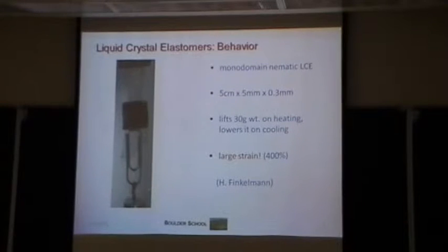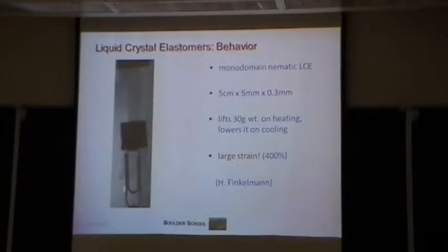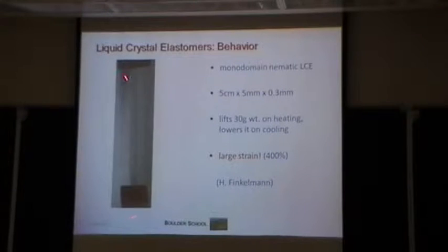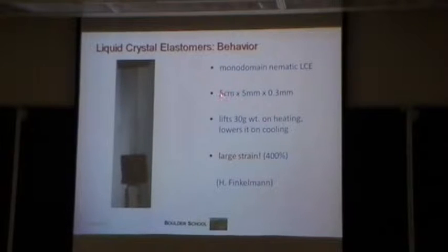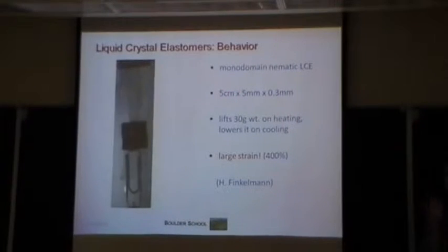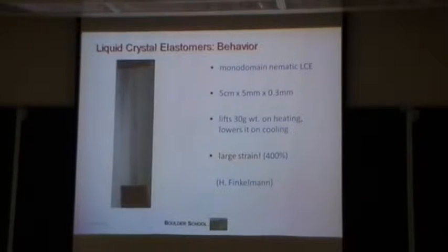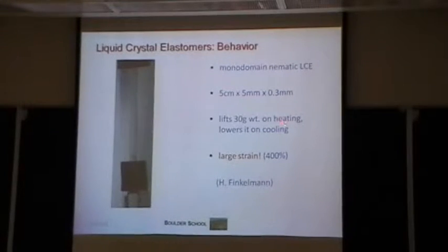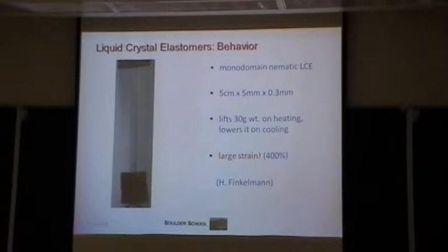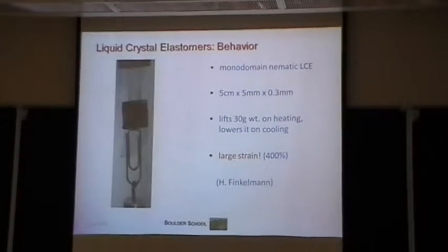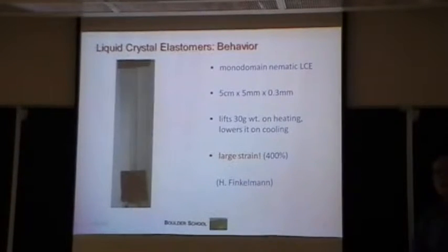Here is a typical liquid crystal elastomer — this demo is something of an icon. This material was made by Heino Finkelmann. It's a monodomain nematic elastomer, about five centimeters long, five millimeters wide, and maybe 300 microns thick. When you heat it, it contracts. Most things when you heat them expand, but this one contracts.